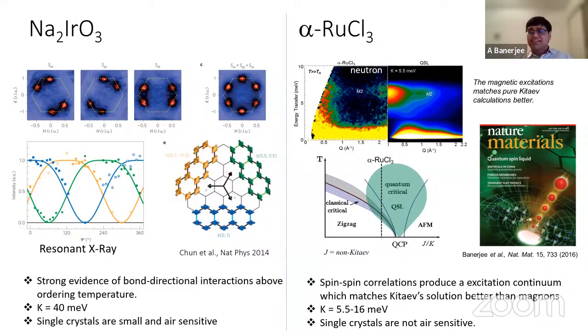It's kind of protected. And if you look at the pure Kitaev interactions and how the spectrum of that would look, we were able to propose that this mode M2 basically has the same kind of features you should expect from an M2 mode that can come from Kitaev interactions. And that was really the Nature Materials paper that we published in 2016. We proposed that it has a Kitaev interaction energy scale between 5.5 and 16 milli-electron volts, and the excitations match Kitaev's exact solution. It is not exactly a spin liquid, but it is very close.